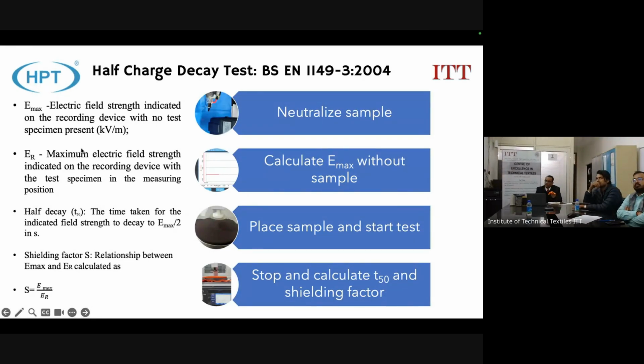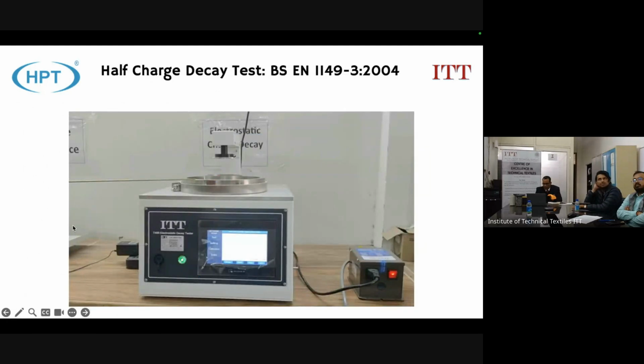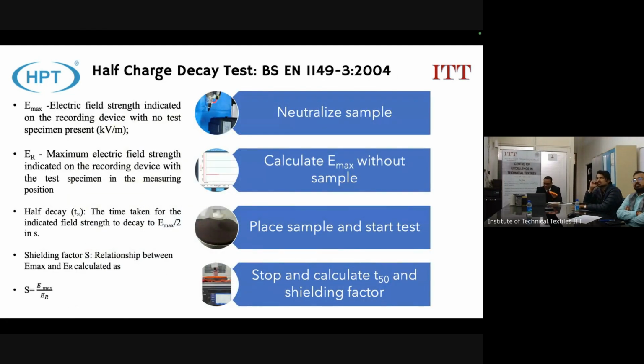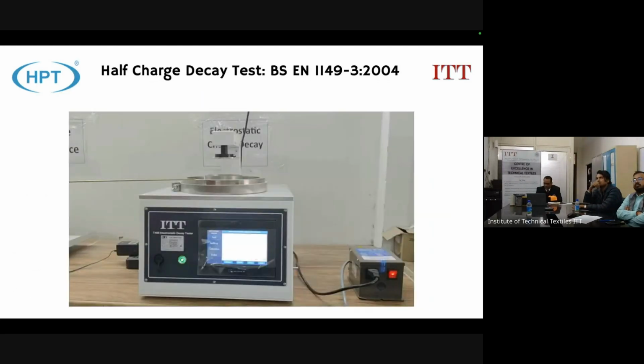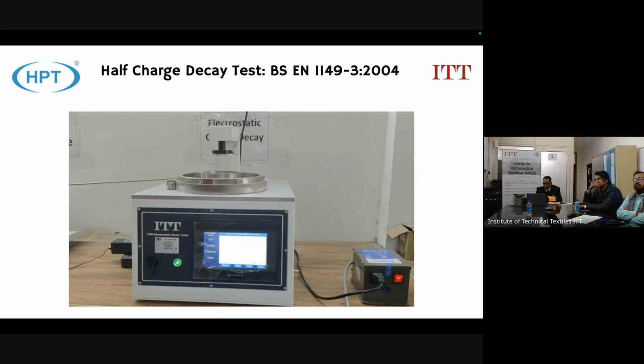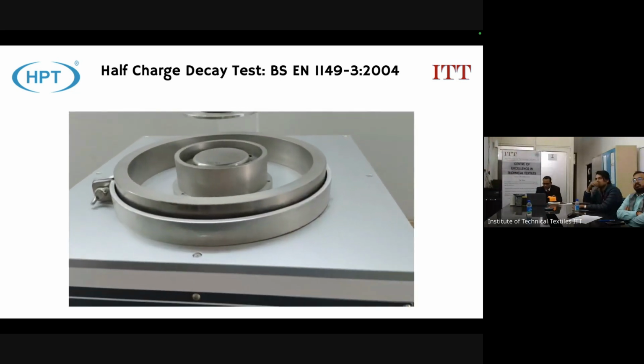In case your sample is conductive, charge will be induced, and the reduction of electric field is measured. So half decay time is reported and shielding factor is reported. Half decay time means 50% of the charge should be dissipated in less than 4 seconds. So this is a small video where we tried it with a normal polymer sheet just to show you.